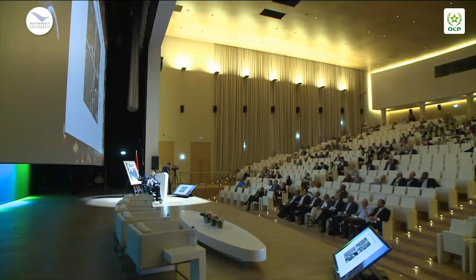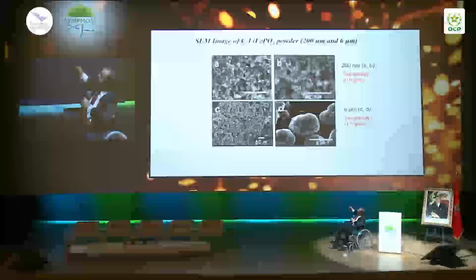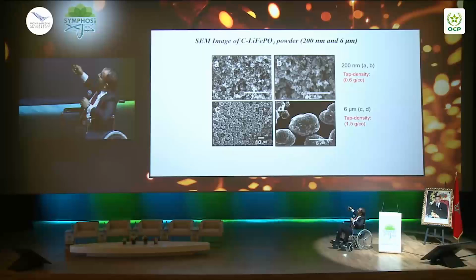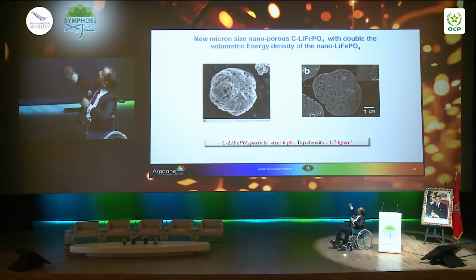So this is how it looks. The material is spherical, as you can see from here. Obviously it's 5 to 6 micron, in some cases 10 micron, so we're talking micron size now. But when you do the cross section, you get a brain-type morphology. So we created nanopores across the particle.